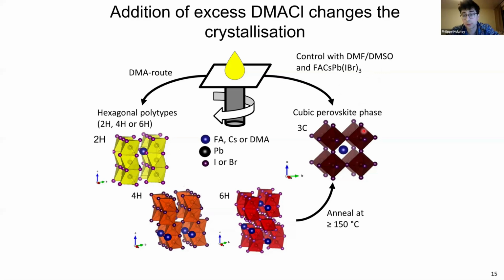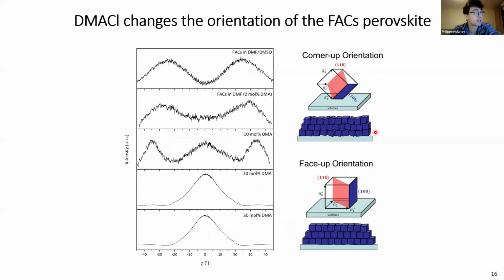One of the big things which we have seen being changed in this is the orientation of the FA cesium film. So here you're looking at a 2D XRD, and you're looking at the cross-section of the cone. So the signal comes out, you get the cone out, and then you look at the cross-section of the cone. So this is the 100 peak, and the cross-section of that. And you see for FA cesium and DMF-DMSO, you have two maxima, which are slightly off from the initial. So they're at an angle of roughly 30 degrees.